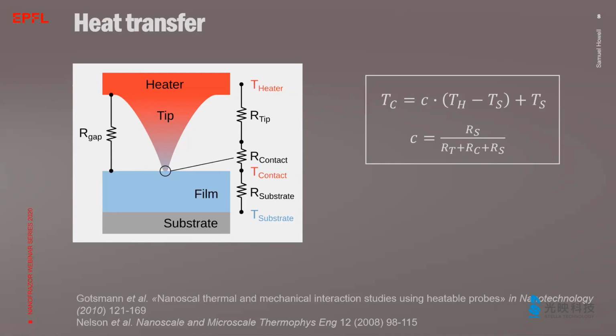So to calculate the temperature of a thin film at the tip-sample contact, often a thermal resistance model is used. The heat transfer from the microheater through the tip apex into the substrate can be modeled as illustrated in the sketch. Based on this model, the tip-sample contact temperature can be expressed as a function of the heater temperature as well as the substrate temperature and the thermal resistances. For simplicity, in this model, we neglect the heat transfer through the air gap. And then the heating efficiency C here is the ratio between the substrate resistance and the sum of all thermal resistances, and determines how much heat is transferred into the film.